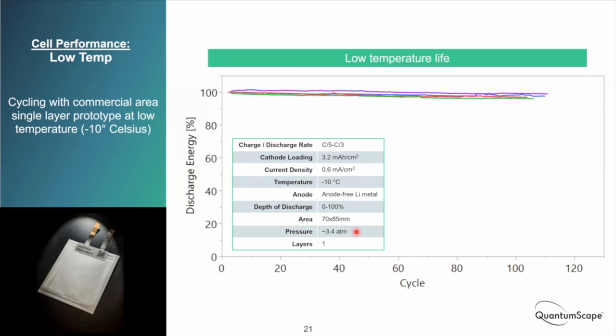The higher pressure you go to, the more volume and mass will be, in a sense, wasted at the pack level to apply that pressure. You're going to need some steel or material in the cell, in the module or in the pack to apply the pressure to a cell. So we're trying to enable low pressures. The range of 3 atmospheres is something that we think might be doable with not too large of a penalty at the pack level, but we also wanted to show that the technology is capable of going to lower pressures.